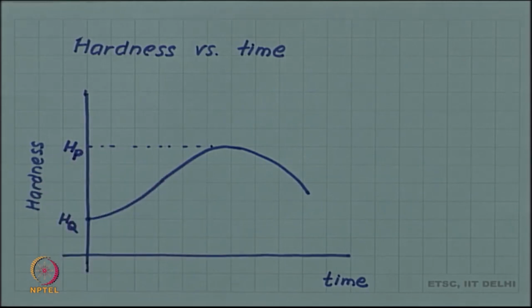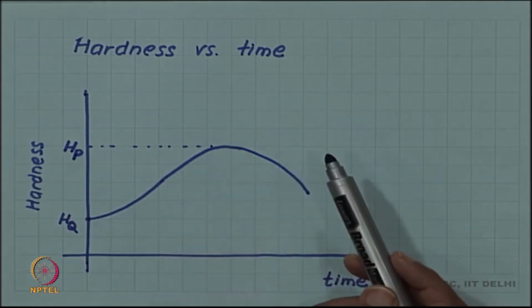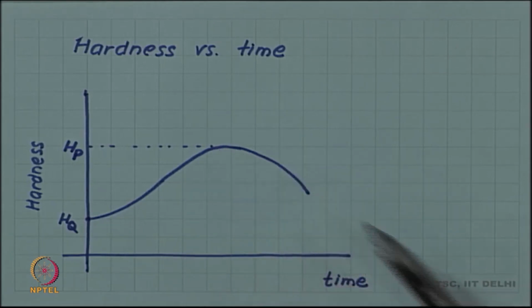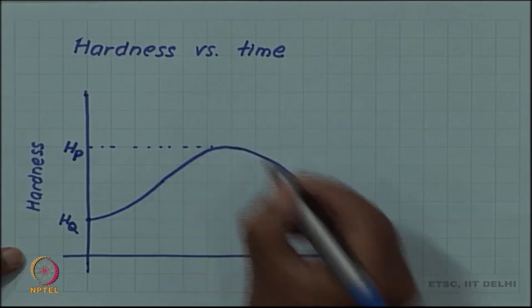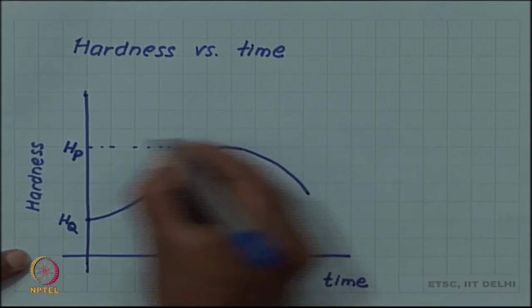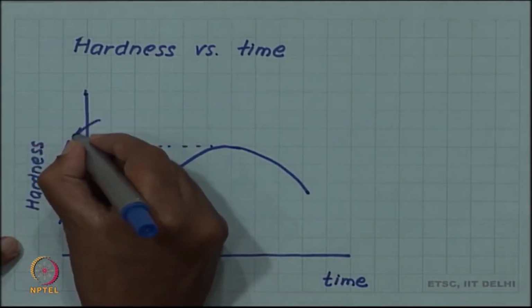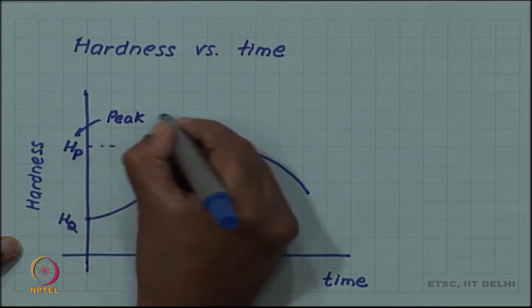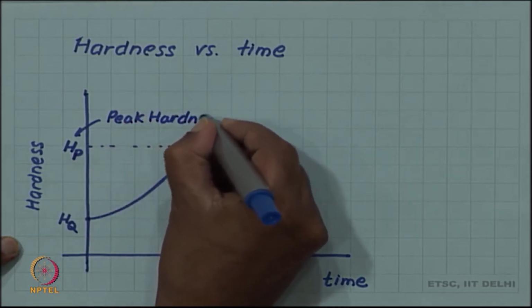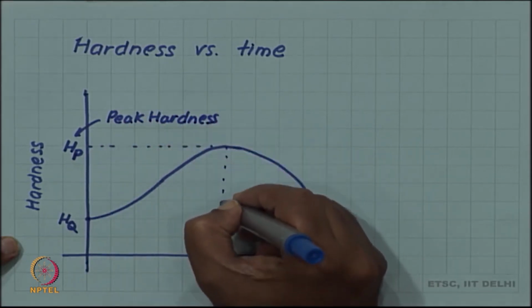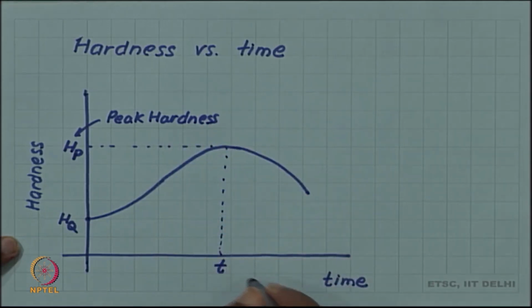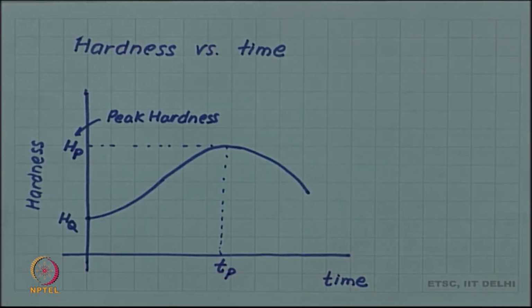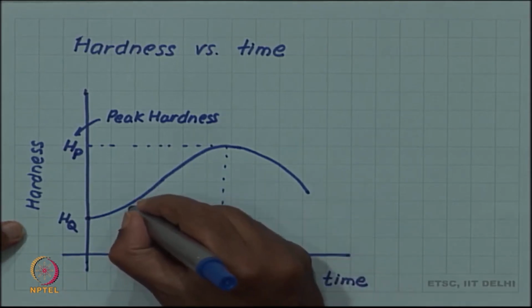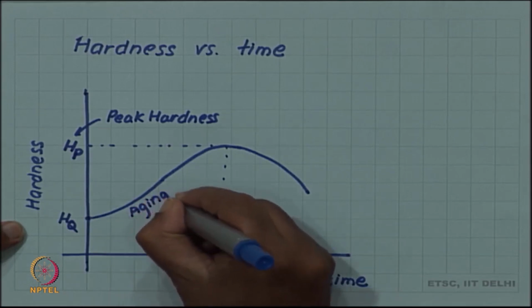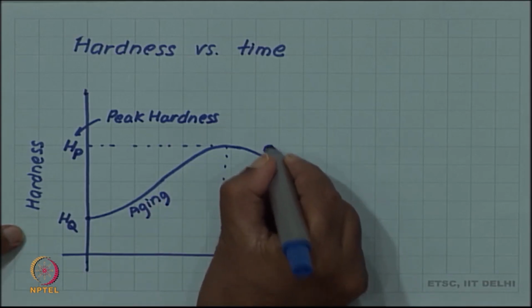So, in fact, there are two surprises: why the hardness increases as a function of time, and then why subsequently it starts decreasing. So, this point is called peak. So, HP is the peak hardness, and the time corresponding to the peak hardness, let us call that TP. So, this part of the curve is called aging, and beyond peak we call it overaging.